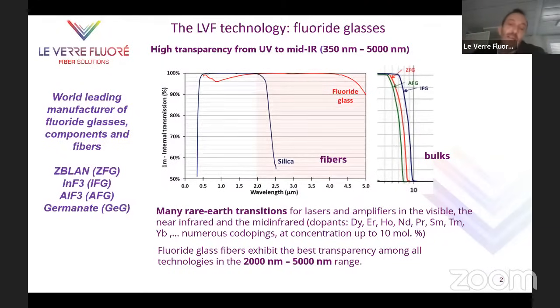Fluoride glass is the best host for very low loss fibers in this 2-5 micron wavelength band. In addition, we can make a new generation of lasers because we can have a high concentration of rare earths, and the phonon energy of our glass is low. So there are many rare earth transitions that lead to many new fiber lasers we are currently commercializing.